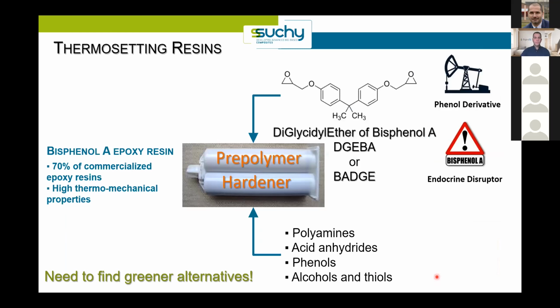So epoxy resins are widely used in the preparation of thermosets because they have excellent thermomechanical properties. And among them, DGEBA resin represent around 70% of the commercially available epoxy resins. And this prepolymer can react with different type of hardeners, such as polyamines or anhydrides. However, DGEBA is composed of bisphenol A, which is subject to strict regulations because it's an endocrine disruptor. So developing a greener alternative for bisphenol A is a real challenge.